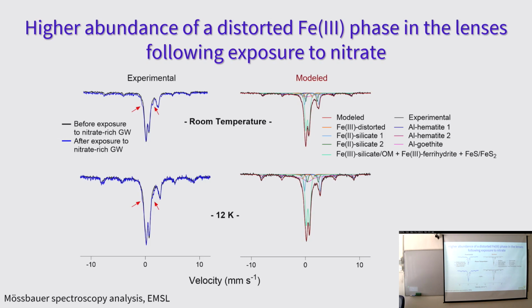But what was interesting here is that we found the presence of a distorted iron 3 phase. Now that phase was found to be more significant following the addition of nitrate, so after exposure to nitrate. That's shown here by the little red arrows. Now I know that looking at this here, it really doesn't look like there's any difference, but there is a subtle difference. It definitely exists, especially in the eyes of a Mossbauer expert, and that does suggest that the process of denitrification is resulting in a higher abundance of distorted iron 3 minerals.